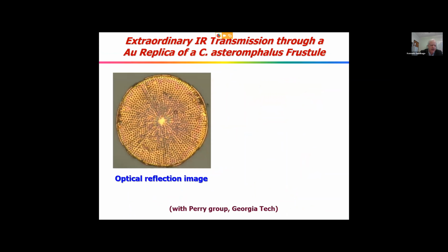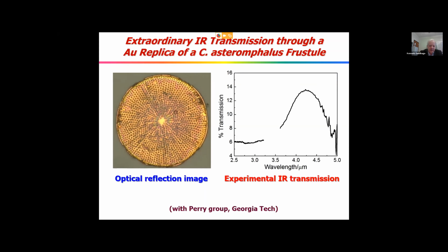So here's an example of a gold diatom replica we made this way with pores that are about a micron or so in diameter. And we checked to see if we could transmit infrared light of a larger wavelength through this. Now, because the pore spacing is not exactly the same, you can actually transmit a range of wavelengths through this material. And in fact, it works.